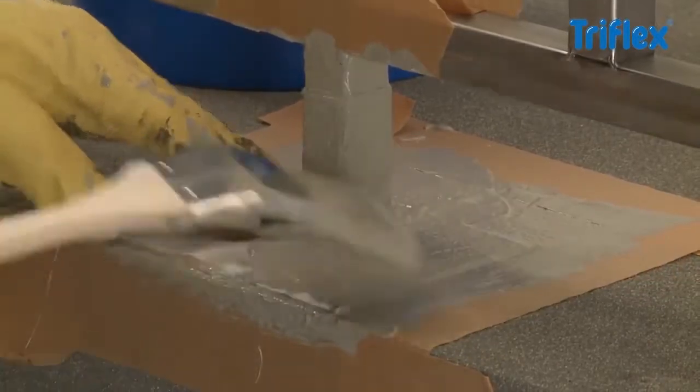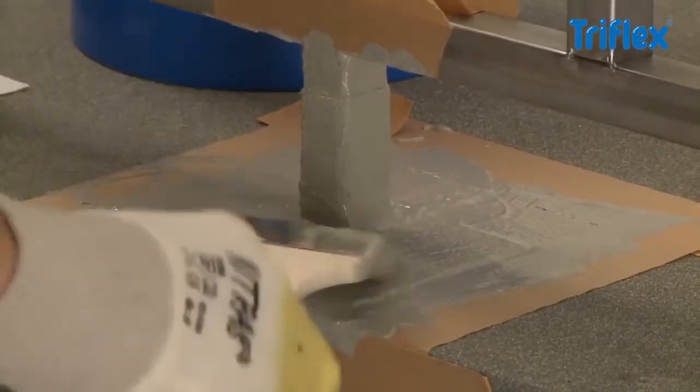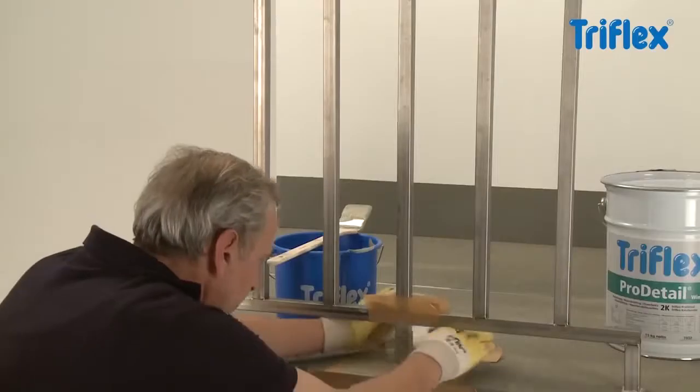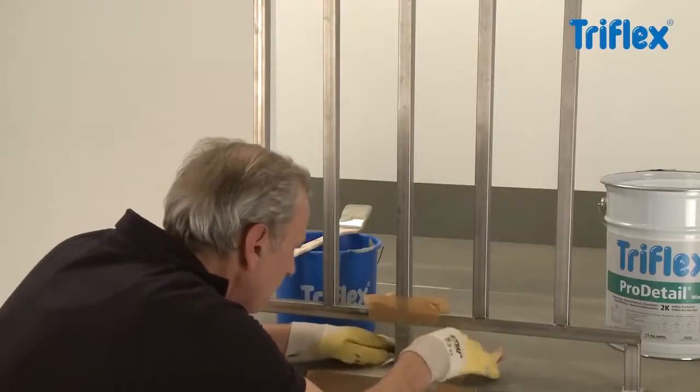Finally, press the two surface fleece sections into position and apply a layer of waterproofing resin. At least 1 kg resin per square meter is needed for the second coat.